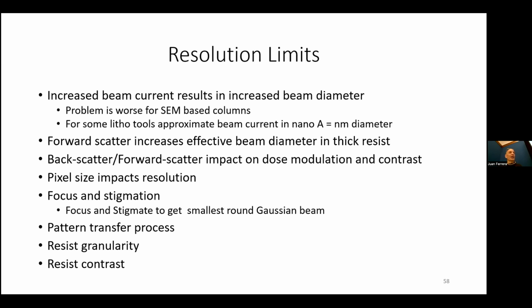Our beam size, we can get down to 1 nanometer. I've even seen work done in transmission electron microscopes where the beam can get down to about 2 nanometers. I've even seen transmission electron microscopes used for lithography with 1 nanometer and smaller beams, but you don't get features that size. There's a bunch of reasons for that. One of them is throughput. If we're going to write with 100 picoamps, it's going to take a really long time to write compared to writing with 100 nanoamps, like 1,000 times probably.